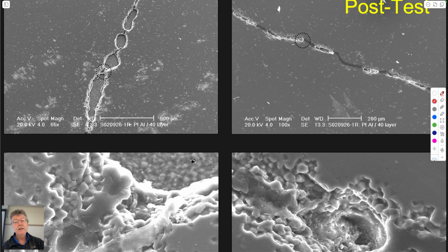You can thin section the sample after you do it. You see some evidence of dissolution due to free face dissolution. You see contacting asperity pits. So this was a sample that was infilled with resin to be able to preserve the sample and then sliced. And this is a thin section slice across the fracture. These are the conduits of the fracture going into the page. This is infilled with epoxy right here. And you can see these asperities keeping it open. It's kind of a nice capillary model if you think about it. A stream tube here, a stream tube here, and a whole bunch of stream tubes here going into the page.